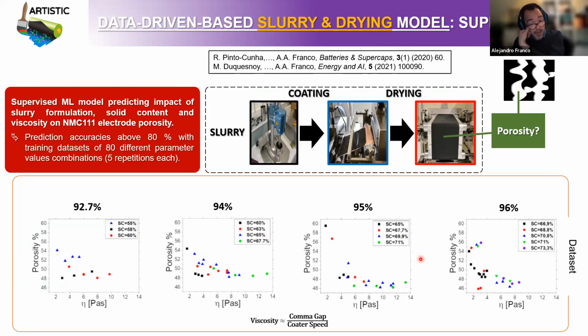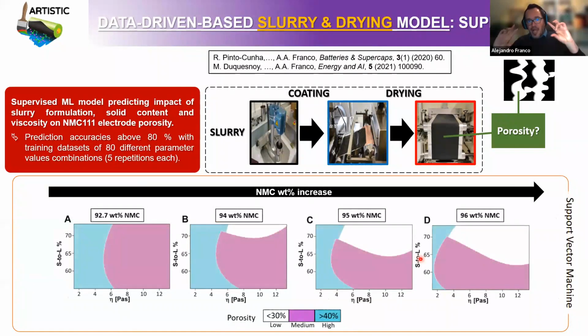So if you apply supervised machine learning, and in particular a technique called support vector machine, you can transform this collection of scattered points into something that is more understandable by humans. You can transform this scattered collection of points into phase diagrams, right? Exactly like in crystallography, but here for manufacturing processes. And these diagrams actually look like this. For instance, you see in this axis the viscosity of a slurry, which is related to the comma gap and the coating speed in your coater, okay? Coating the slurry, which then goes into the oven.